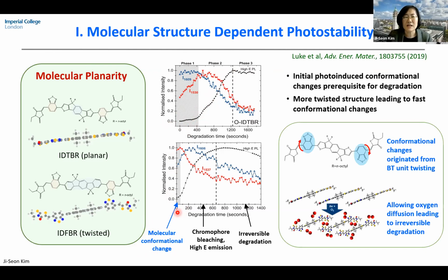From this comparison of the planar and twisted molecules, we understood that such a structural change comes from the unit where there is no side chain attached, so it is very easy to rotate, for example, the benzothiadiazole unit in IDTBR NFA materials. This conformational change, particularly the BT unit twisting, will induce the conformation from the planar to a more twisted structure. When you twist the molecule, of course, there is a higher probability for oxygen and water to diffuse in and then cause this irreversible degradation.